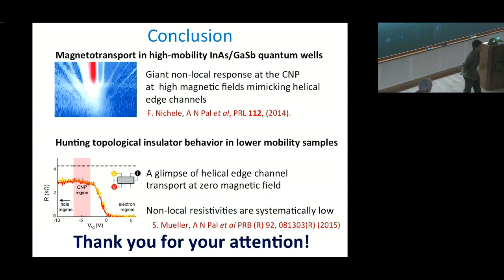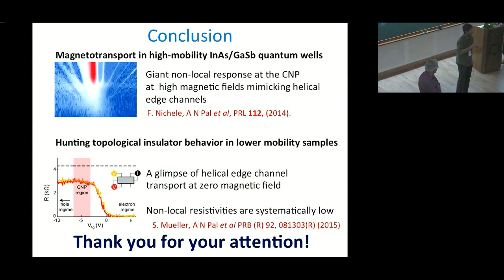Question about how the hybridization occurs: in the Hamiltonian, indium arsenide has an S-like conduction band, and the hole-type band comes from the gallium antimonide P-type states. You have to find states of the same momentum. The J=1/2 states of the hole band couple to the J=1/2 electron states, giving rise to a k_x + ik_y type dependence in the off-diagonal term of the Hamiltonian.